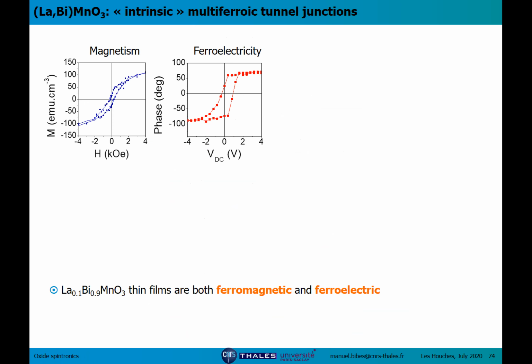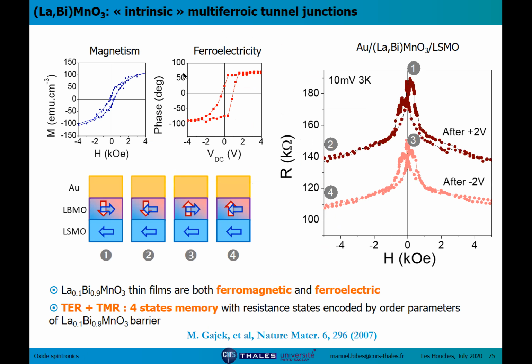So bismuth manganite is quite difficult to grow. Lanthanum helps a little bit to get better films. And we could show that these films can be at the same time magnetic and ferroelectric. So ferroelectric at room temperature, magnetic below 100 K. And we integrated them into tunnel junctions. So we had LSMO, LBMO, gold tunnel junctions.